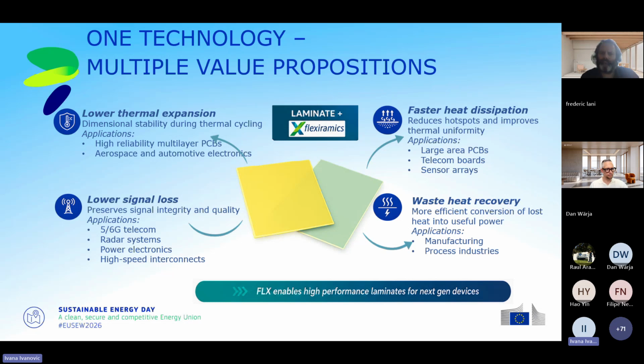We can talk about the lower thermal expansion, which gives dimensional stability, so the CTE is close to copper. We can talk about faster heat dissipation, especially in the lateral XY direction, compared to the commonly used glass cloth. It has 4 times better thermal conductivity. It shows 70% less signal loss compared to the same glass cloth in 6G or other systems. And last but not least, it has more efficient energy recovery, or waste heat recovery. So that is where we find a place in the new architectures of thermoelectric generators.